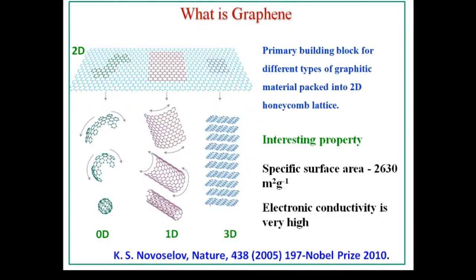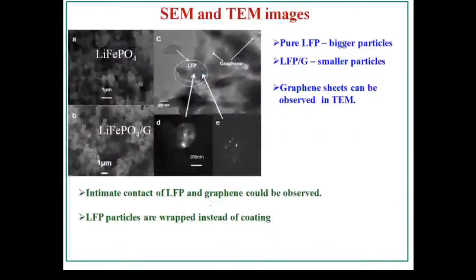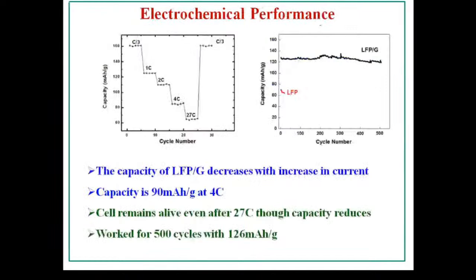Anyway, how is this material helpful? This nanomaterial helps improve the chemical or physical property of our battery material that I have shown. These are the SEM and TEM pictures. Here I am showing the nanomaterial. And LiFePO4, we coated it with graphene, and it is not basically coated, it is wrapped. And we checked the electrochemical performance, and here also very clearly you can see that we could run around 500 cycles, whereas the bare LFP, the red one, could run only 15-20 cycles.